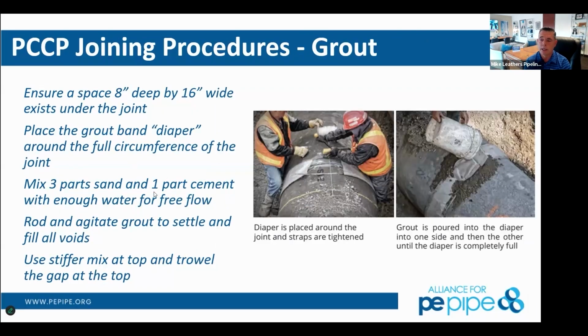So that grouting may sound easy, and hey, I just got to pack some cement around, some grout around the joints, but it is very complex and challenging and must be done successfully. So even if the labor gets under that pipe and gets that grout where he's supposed to get it and has this 8-inch deep by 16-inch wide space under the joint, they still have to get that grout around in that sleeve. And so what happens a lot of times is these guys just add a whole bunch of water to their mix and that pushes that grout all the way around easily. But now you got a higher water cement ratio, and that's probably going to crack.